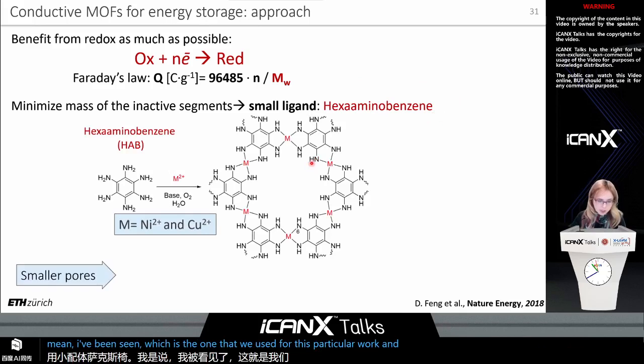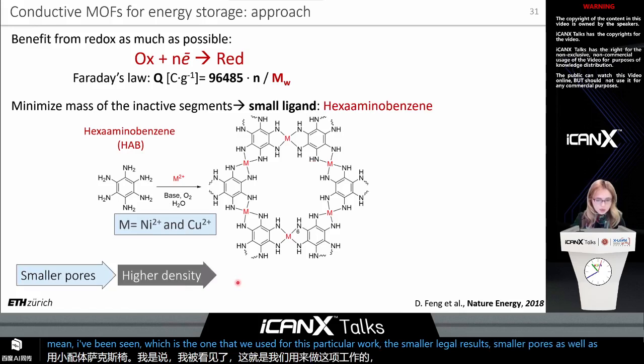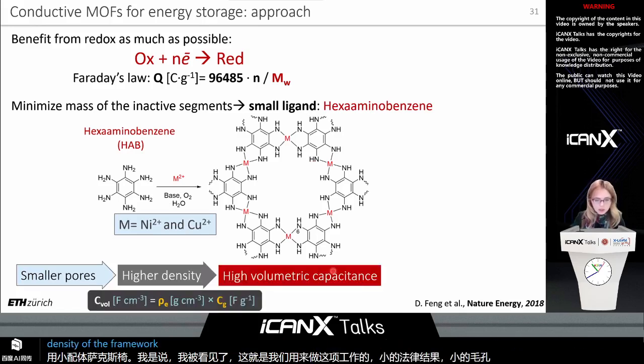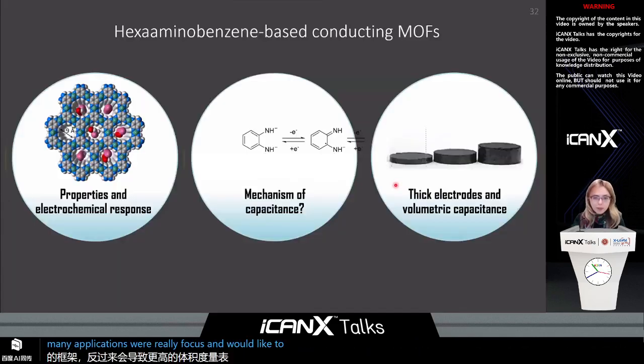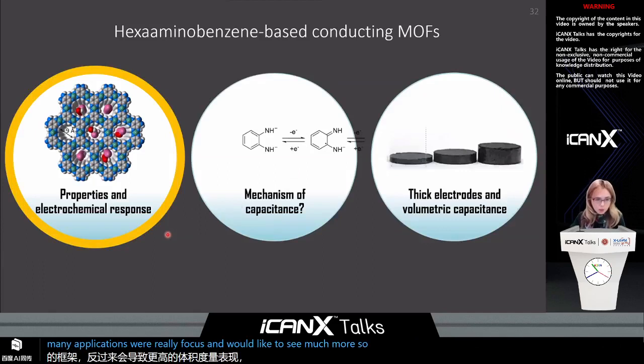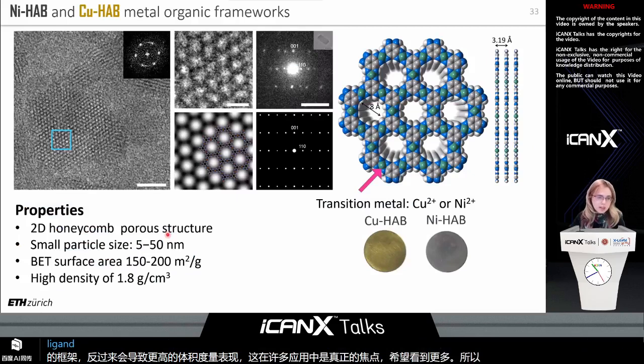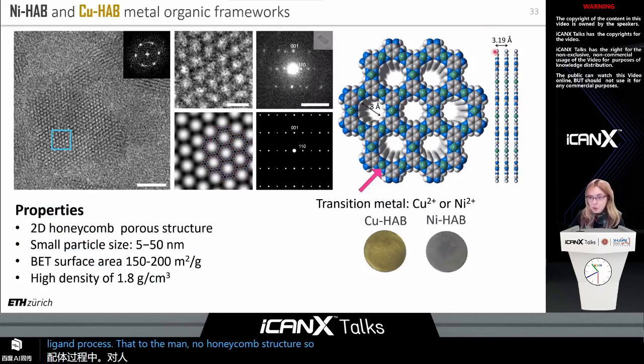This smaller ligand results in smaller pores, as well as higher density of the framework. And higher density of the framework would in turn result in higher volumetric performance, which in many applications we really focus on and would like to see much more. So these frameworks based on this small hexaaminobenzene ligand possess a two-dimensional honeycomb pore structure. These are actually also two-dimensional materials, but they have pretty strong pi-pi interaction between the layers.